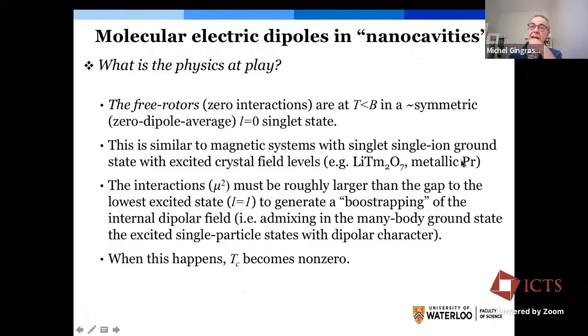And as well as metallic praseodymium. Praseodymium as a metal would have a singlet ground state. It shouldn't be magnetic, but because of the low-lying crystal field level of praseodymium, praseodymium as a metal is actually magnetically ordered at low temperature. So the interaction here, the dipole-dipole interaction, admixes the excited rotational states into the ground state, entangling them into that state. And ultimately, this bootstrapping leads to the development of an internal dipolar field, which gives rise to collective long-range order if the dipolar interactions are large enough.